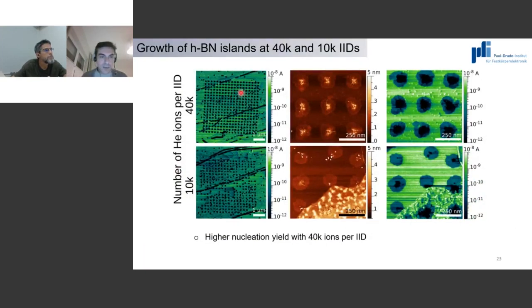And if we look closer, we indeed see that we were able to nucleate these islands where we wrote the defect. We still see some parasitic growth happening, as expected, as I showed you before. But the bottom line is that indeed you have preferential nucleation around defects. And what is actually nice to see is that if you use 40,000 ions per defect, we probably, I mean, we're still looking into that, but we probably kind of dig a hole in graphene.